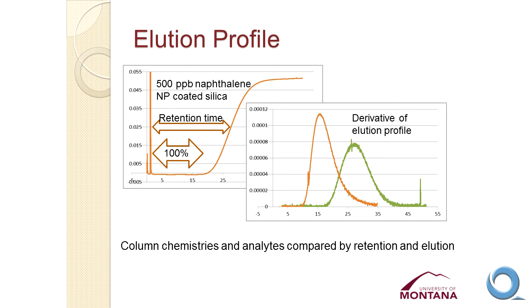So this is what a typical elution profile looked like as we did these experiments. We're starting right here where you see that big spike. We're switching that valve and starting to introduce 500 parts per billion naphthalene in water. We don't see any absorbance for the naphthalene for some period of time. This is a column, the silica that was coated with one of the nanoparticles. And we don't see any signal for the naphthalene for some period of time, greater than 15, 16, 17, 18 minutes here. And then we start to see the signal go up as the naphthalene breaks through the column.